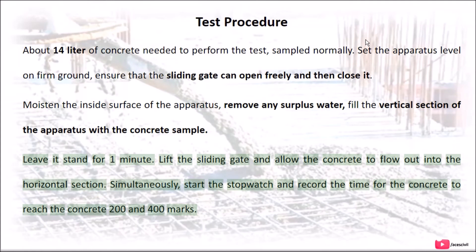Leave it stand for one minute. Lift the sliding gate and allow the concrete to flow out into the horizontal section. Simultaneously, start the stopwatch and record the time for the concrete to reach the concrete 200 and 400 marks.